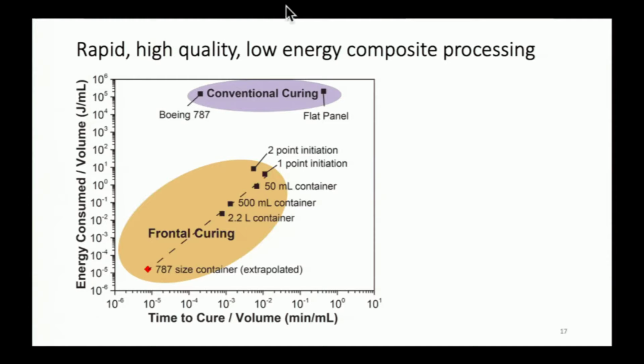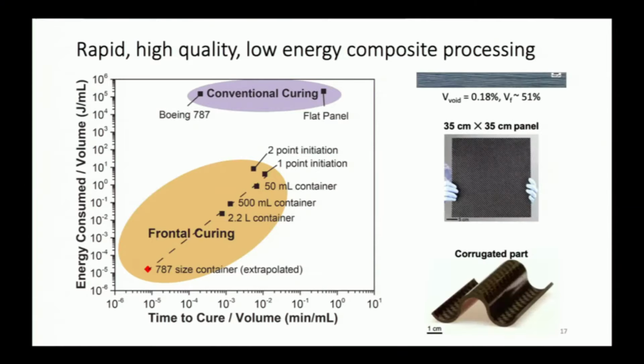It's a relatively slow process on a volume normalized curve. And it's also a very energy intensive process, again, normalized per unit volume. If you were to compare that with our extrapolated calculation of what that section of the fuselage would have been in terms of an energy input where there had been just a single point trigger, soon that front spreads, there's quite a bit of volume being polymerized at any given time. And so by that means, it really is a very energy efficient process. And some of the materials that we can make and the ability to really break away from the autoclave and do molding in new and unconventional ways is really very exciting.